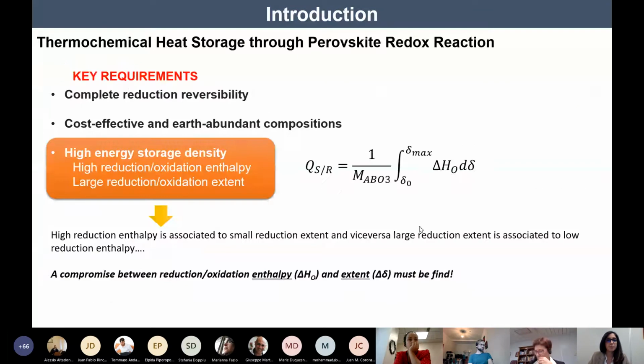Okay, so one of the key requirements for the materials to be ideal candidates for thermochemical heat storage is to have very high energy storage density, of course. As we can see from this equation, it is important to have not only a high reaction enthalpy, but also a large reduction extent. However, in reality, a high reduction extent is associated with a small reaction enthalpy, since it is directly connected to the energy that is necessary to reduce the material. So a compromise between the reaction enthalpy and extent is needed in order to find a good candidate material.